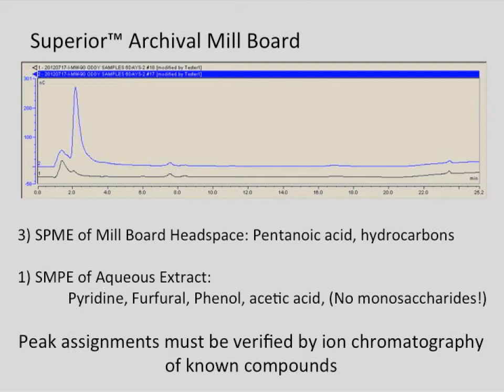So then we looked at the aqueous extract and found these compounds. Note that I'm sort of cherry picking compounds from these mass specs - the mass specs are complicated, and getting accurate identification of the peaks would take a lifetime if I looked at all of them. I'm using a library to assess my results and taking things that have a high confidence of identification using those libraries, which makes sense with the materials I'm looking at.